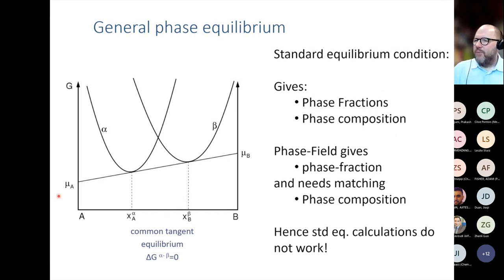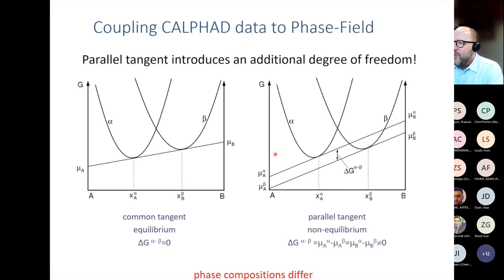So from that, we can then actually start combining curves of these. Let's say here one for alpha phase, one for beta phase. We can define a common tangent. I'm sure we've all seen that at some point. And from the common tangent, we get our phase equilibrium. That's the basis for what's done in the CALPHAD method and the appropriate software that uses the CALPHAD method. In phase field, we've been using a similar approach as well in order to describe equilibrium in the local equilibrium approach. But in phase field, it was necessary to introduce an extra degree of freedom. And that was a very big challenge to overcome in the early 2000s in order to get the coupling to the CALPHAD databases to work.